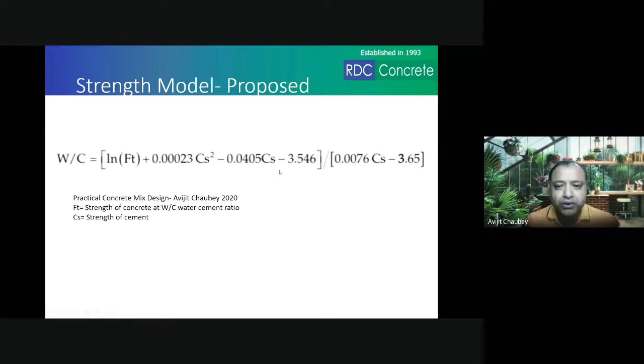So you can plug in the CS value at these respective places, and whatever strength you want, you can put it. Let us say you want 35, you put the 35, and let us say the cement strength you get is 58, you put 58 in all these places, then you will be able to get what water cement ratio you require to get the strength of 35, and so on. Or you can do vice versa. For the water cement ratio and that cement strength, you can calculate what strength you will get.